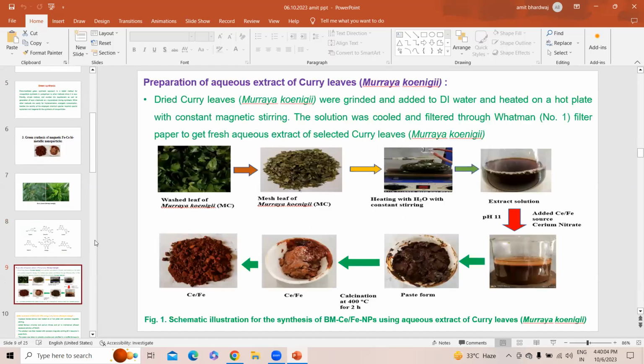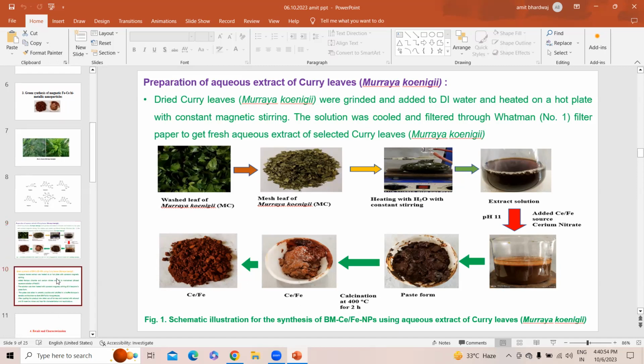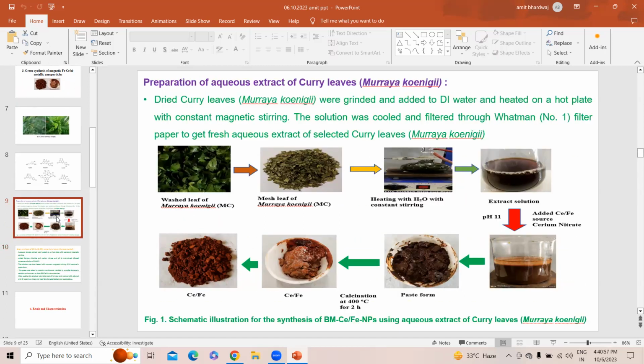Firstly, I took curry leaves, washed them, dried and crushed them. The crushed particles were kept in distilled water for 4 to 5 hours, and then the extract was filtered. In this filtered extract I poured two salts, cerium nitrate and ferric chloride, mixed them together and heated on a magnetic stirrer until dryness. After dryness, the paste was taken in crucibles and kept for 2 hours in an open furnace at 400 to 500 degrees centigrade. Then I washed the material with distilled water and ethanol 4 to 5 times, and used this powder material for characterization.